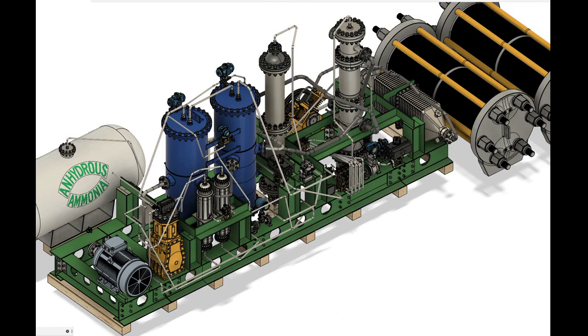Since 178 kilograms of hydrogen is required to produce 1 ton of ammonia, assuming no losses to the atmosphere, the minimum energy consumption is around 7,000 kilowatt-hours. Nitrogen must then be compressed from 1 bar to roughly 1 megapascal, to facilitate the pressure swing adsorption process needed to produce the highly pure nitrogen. This is a convenient feature, since the diaphragm compressor for the synthesis compression requires an inlet pressure of at least 1 megapascal to operate effectively.